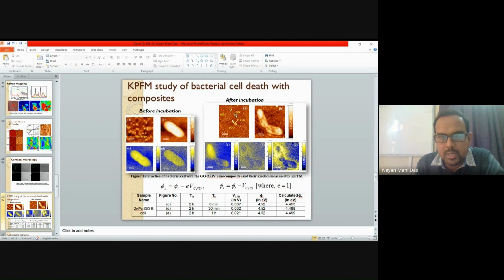But when we did the incubation, that is for our H aggregate composite material, we could see that the bacterial cell, when it gets incorporated, this is the topography. Over this graphene and the bacterial cells, we could see that there is a charge assimilation as the time passes. This is at around 0 minute, at the initial part. This yellow mapping color is basically the charge possessed by the bacterial cell, which is also shown here before the incubation. As the time period changes, this yellow color, the charge shown by the yellow map, starts to assimilate with the surface, which is the ZnPc surface.